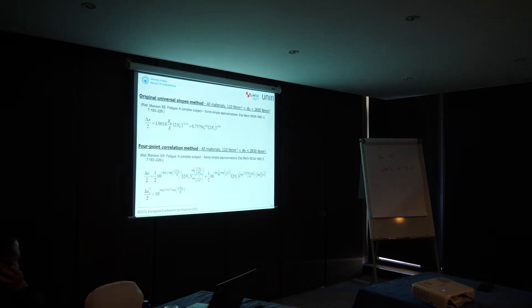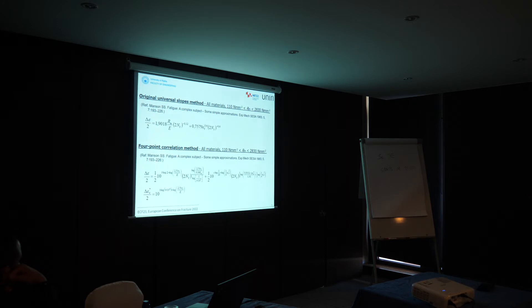Regarding the models we are dealing with — primarily the Basquin-Coffin-Manson fatigue model and parameters for crack initiation or time to failure — the idea is to try to determine them from monotonic material properties. As for existing models and expressions developed over the past time, I will not go into details, but here are the most illustrative ones. The first, so to say, was the original Universal Slopes method, which is rather compact and elegant — fatigue strength coefficient is estimated just using ultimate strength.